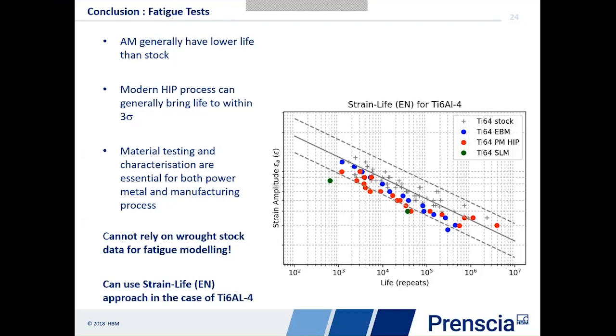Material testing and characterization are really essential when you're looking at both powder metal and additive manufactured processing. You can't just use the fatigue properties of the wrought stock data. You've got to go and measure them, and that has to really include the process that you're using, the manufacturing process and the heat treatment process afterwards. But one of the really nice things to come out of this is that it's proving that we can use ordinary strain life methods in the case of this Ti-64 to predict the fatigue of additive manufactured components. And that's something new. That's something that we didn't necessarily expect at the beginning.